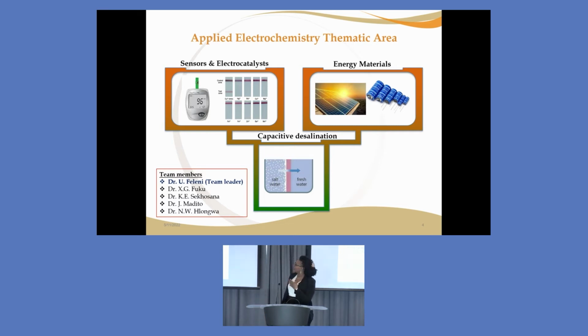So when we synthesize these nanomaterials, we usually use stabilizing agents. These stabilizing agents normally have thiol groups, carboxylic groups, and amine groups. The reason for using stabilizing agents when we synthesize is because we want to improve the stability of nanomaterials and also to tune the sizes of the particles. So in this thematic area, we have sensors and electrocatalysts. So it means that when we synthesize and characterize these materials using various instrumentation for optical properties, morphological properties, and electrochemical properties, we apply them in sensors and electrocatalysts.